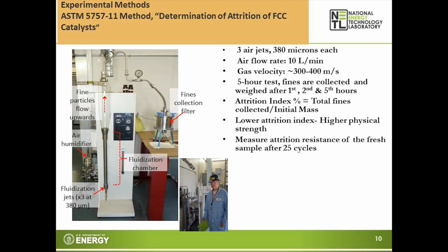The other important parameter that we measured is the attrition resistance. The material has to move from the air reactor to the fuel reactor and back and forth, so it has to have high physical strength. So we use the ASTM method to measure the attrition resistance of this material. The unit has 3 air jets, and we introduce air to the material at a very high flow rate, and we conduct the test for 5 hours, and we collect the fines during the 5 hours. Attrition index is defined as the total fines collected divided by the initial mass. So if we get a low attrition index, that means the material has high physical strength. So we measure the attrition resistance of the fresh material and also of the material after the 25 cycle methane and air CLC test.